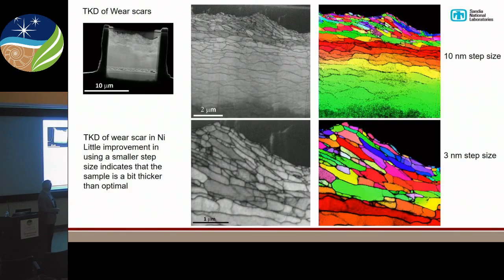Here's an example from a wear scar. So we have a lot of work at Sandia in contacts, switches, all that sort of thing, because we'd like to know how long they're going to last and whether they're going to be reliable. So we do a lot of measurements. So here's our thin sample. This is the wear scar. You can see the fine-grained region. This is a FIB-prepared sample.